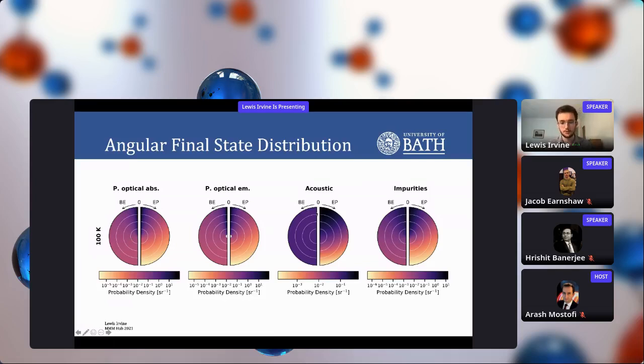What is different, remember, is that acoustic scattering was significantly changed. You can see there's a qualitative change here. At 100 Kelvin, acoustic phonon scattering is basically elastic, and it's also anisotropic. But introducing the electron polaron terms changes that significantly to be strongly forward scattering. So that's what affects the change in the rates. And then as you go to 300 Kelvin, so we increase the temperature, you can see that all these differences fade away. They become less significant.